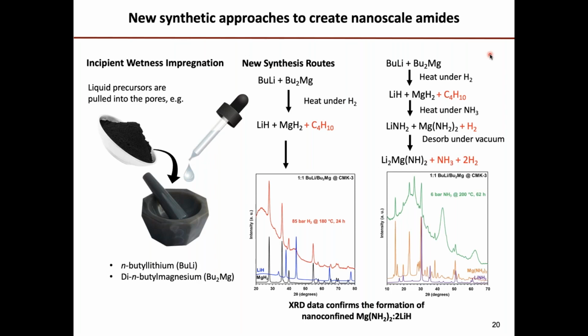And basically what you do is you take some precursors to the lithium and magnesium, you put them in a solvent and submerge the porous carbon in that, and these nanopores will wick in the solution and fill up, and then you can react that with hydrogen, or you can react it with hydrogen and ammonia, a couple of different reaction schemes that are shown there, and generate the lithium magnesium amide, or if you drive off the hydrogen, you can get an imide. So that's the basic reaction that occurs.